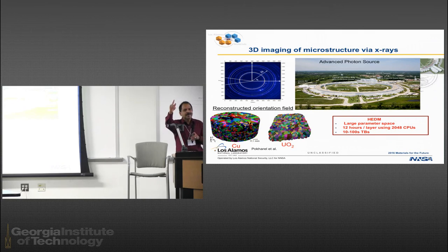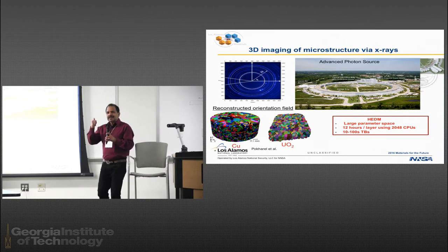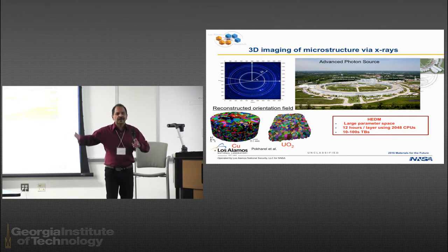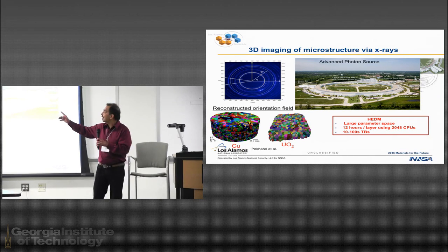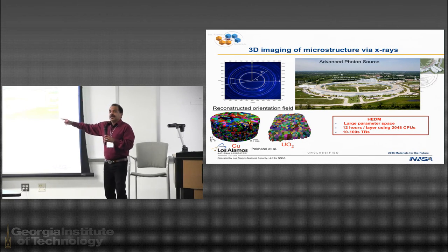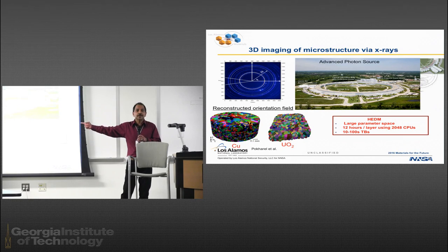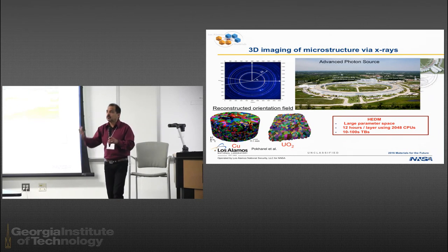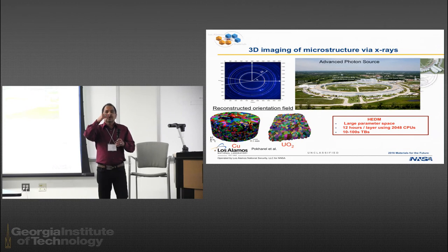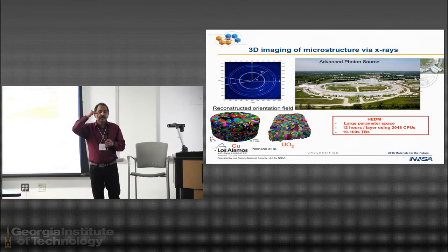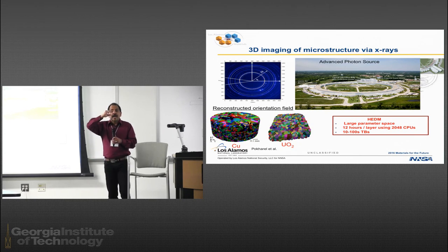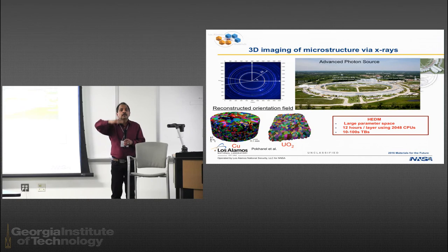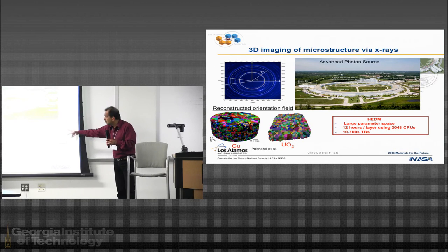But then you have a big jump, in that the data sets now are of the order of terabytes, tens to hundreds of terabytes. And here, the whole idea, and it's a challenging problem, is reconstructing microstructure. Okay? So you basically shine photons, the light source, onto a given layer, and layer by layer you build this microstructure, reconstruct the microstructure. It's very, very slow. The analysis, as I will show you, is brute force.